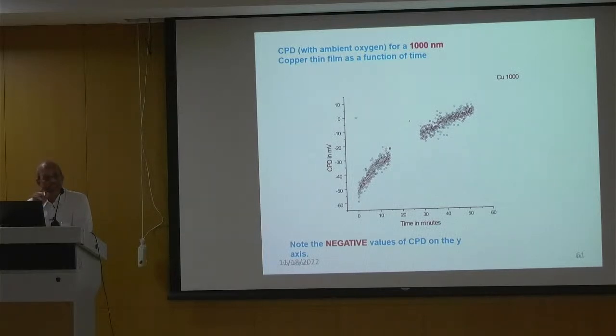Naturally, these two positive and negative reactivities are different, because of thermodynamic equilibrium: the free energy of the surface and the Gibbs free energy for oxidation are different. So this experiment has answered the question. Following the dynamic oxidation of copper, not only the nature of the surface is known, but also the oxidation kinetics